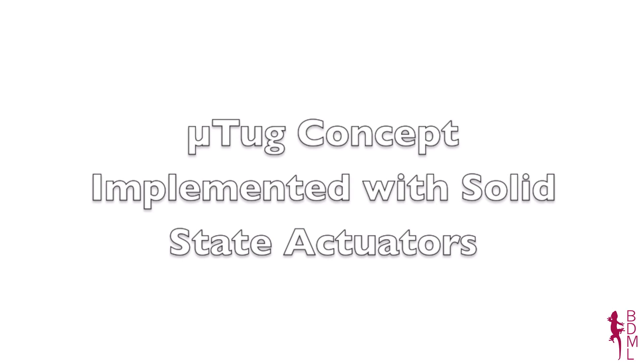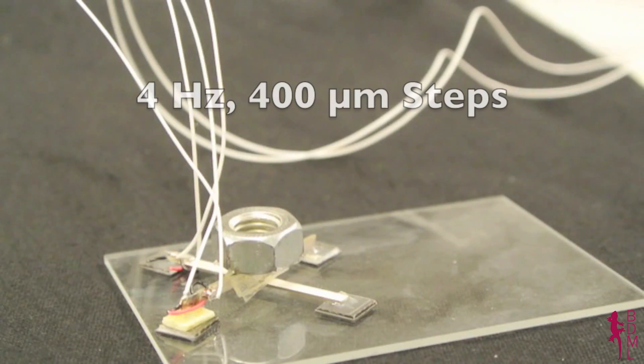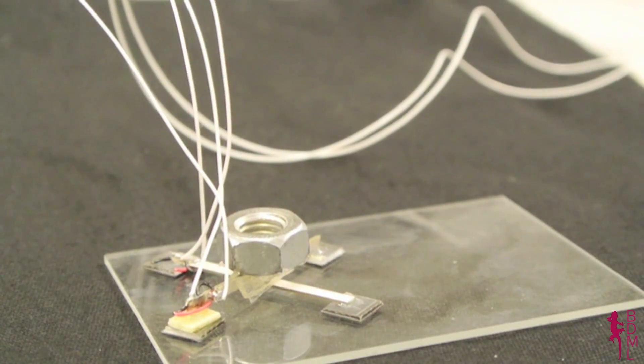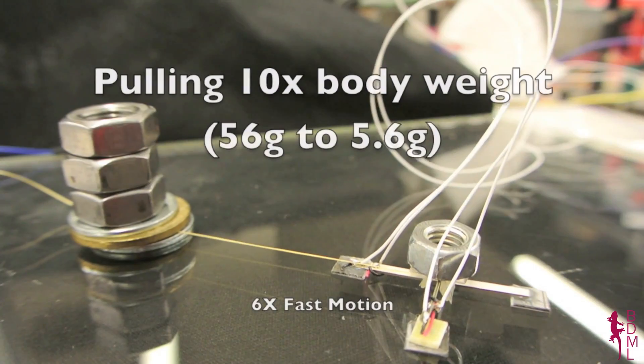The same principles can be used for solid state actuators that would be necessary for further size reduction. Piezoelectric PZT bimorphs demonstrate the adhesive's impressive speed, but for reasons discussed in this paper will be limited by the amount of work per cycle they can achieve.